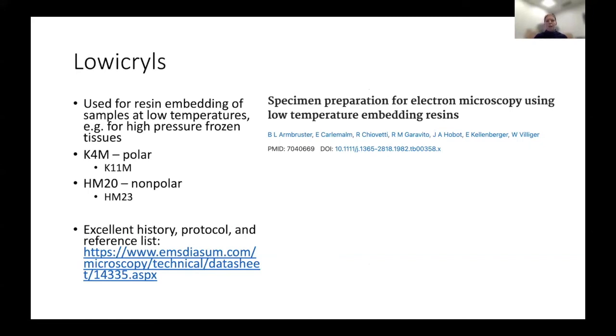These are resins used for embedding samples at really low temperatures. So this is used in association with, for example, a high pressure frozen sample. So if you want to avoid chemical fixation, in fact, I think the last time I gave my Beyond the Scope talk, it was about high pressure freezing. So if you have a high pressure frozen sample, you pretty much have two options. You can either take it through a freeze substitution step where you replace the vitreous ice with a chemical fixative as it comes back to room temperature, or a chemical fixative with a heavy metal stain in it so that it comes back to room temperature, and then you can embed it in a room temperature resin, one of the other resins. Or you can infiltrate it at a very low temperature in a Lowicryl, a resin that is made to work under very cold temperatures.